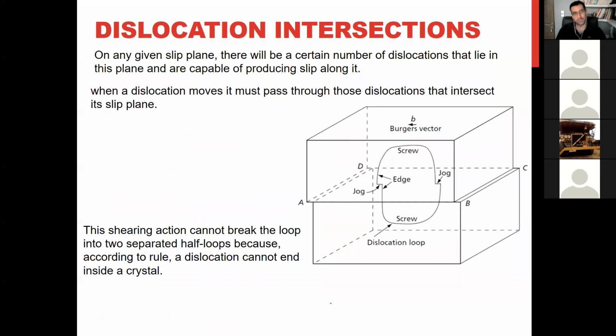Another thing happens inside of metals like FCC. You know, I told you FCC has 12 slip systems. For example, we have 4 slip planes, and they make angles with each other like this, okay? If we have a dislocation in this plane and a dislocation in this plane, and both are activated or moving, in some places they intersect, yeah? So when dislocations intersect with each other, they cannot cut each other cleanly. For example, if this is a dislocation loop inside of a metal and a dislocation from another plane is coming here, when they intersect, these steps will form.